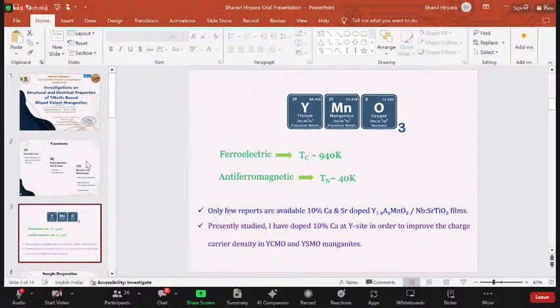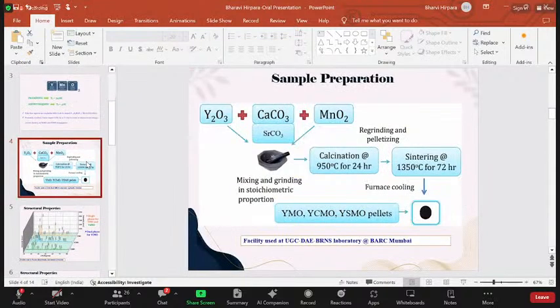Shortly, YMnO3 manganites have been used widely for memristive and resistive switching kinds of applications, because they show ferroelectric and antiferromagnetic transitions, and with a little bit of perturbation their properties change. Here I have studied 10% doping at the Y site of YMnO3 compounds. The samples have been prepared from the oxides by the solid state reaction route, by consecutive calcination and sintering, then final pelletizing, to obtain pellets to be used as PLD targets. The samples have been prepared at the UGC DAE BRNS laboratory at BARC Mumbai.